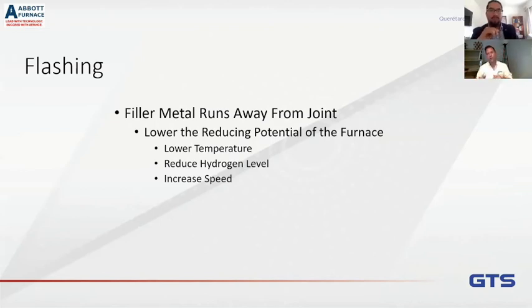that it runs everywhere. So really the solution, when you tell a production person that they're allowed to increase the speed to get rid of a problem, honestly, I've had them look at me like, really? You're lying, I'm never allowed to increase speed. But yes, you can increase speed, reduce the time that you're in that reducing zone, or lower the temperatures, or reduce the amount of hydrogen. But I would start off by maybe reducing the hydrogen a little bit because that's expensive, and then increase your speed a little bit, and then only adjust your temperatures.